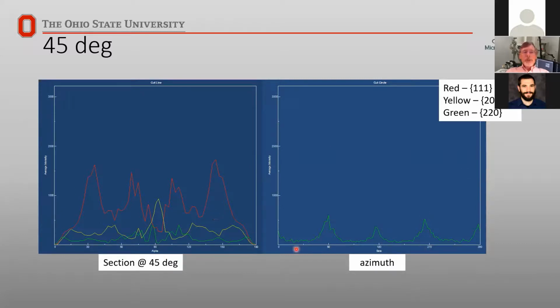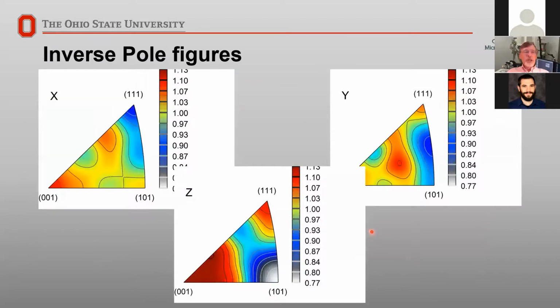So this is showing me the distribution of 3 different sets of planes. My 200, or one of the faces of my cube, is sitting up at 90 degrees, which would be parallel to the surface of my sample. So taking all these 3 planes now, I can start to work out and get a complete orientation distribution function. And I can express that in a number of different ways. But here is one example showing what are called inverse pole figures, in the X, Y, and Z directions, showing where those poles are distributed.